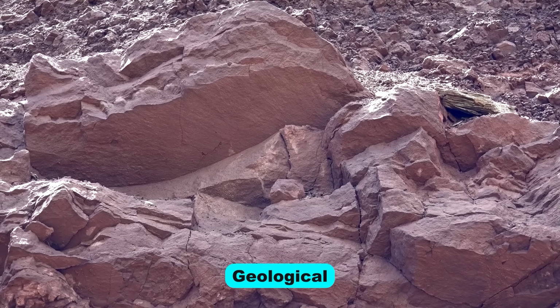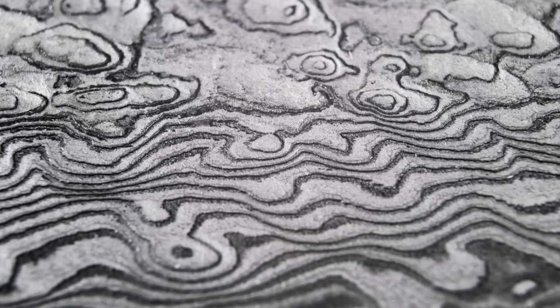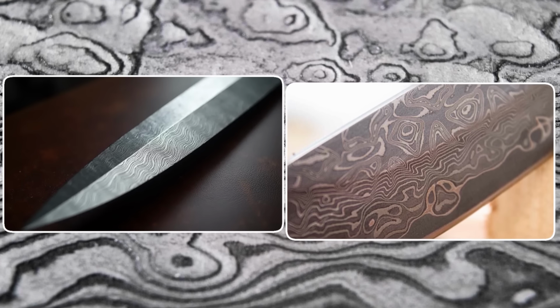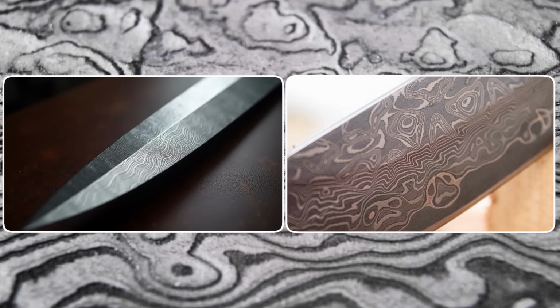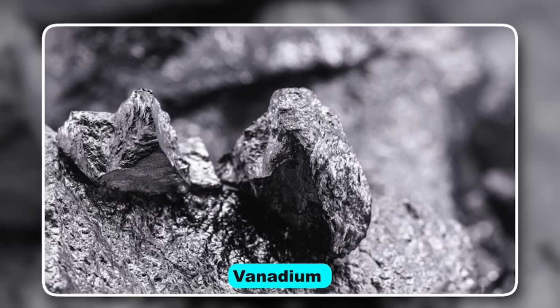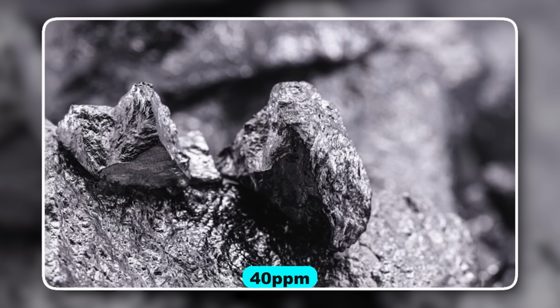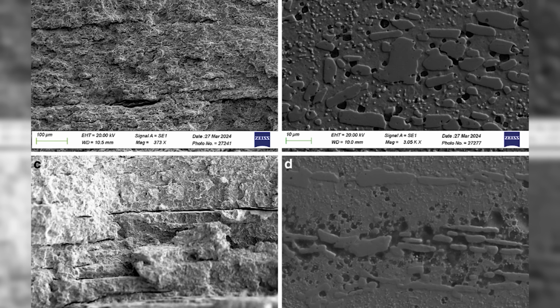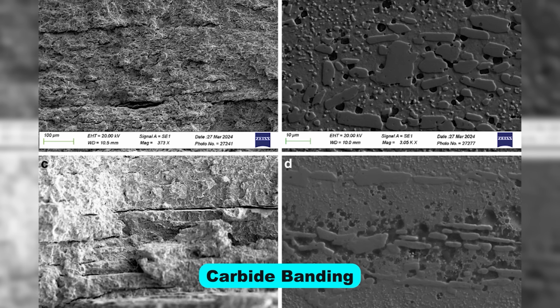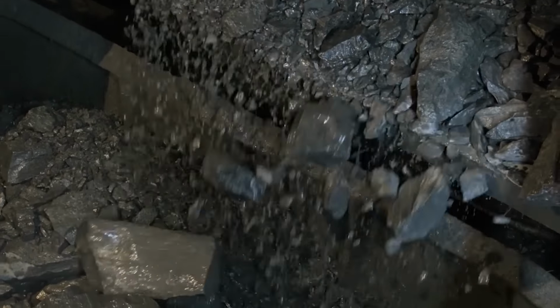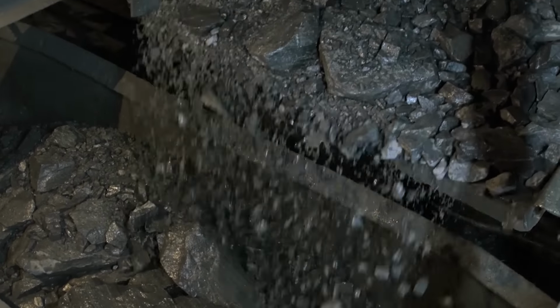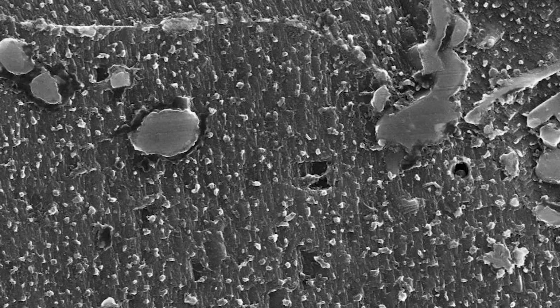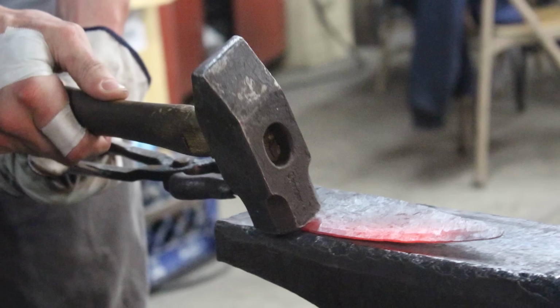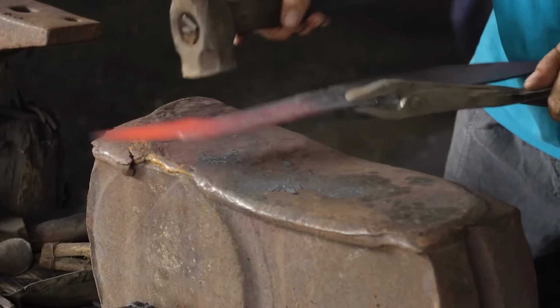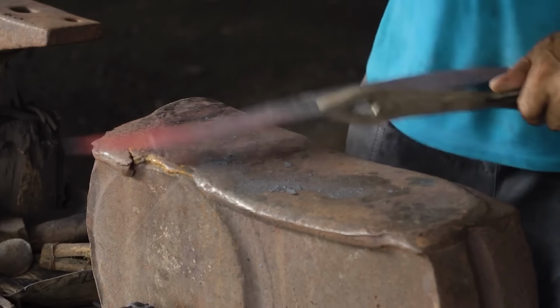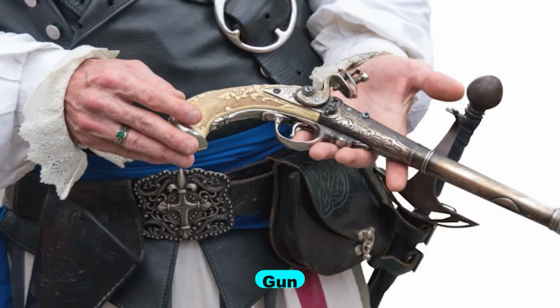The second force was geological. Verhoeven and Pendray's research demonstrated that the famous Damascus pattern depended on trace impurities in the original Indian ore, specifically vanadium at concentrations as low as 40 parts per million. Only certain deposits in certain regions produced steel that could develop the characteristic carbide banding, and when those specific deposits were mined out or became inaccessible through political disruption, the raw material for true Wootz disappeared along with them. Smiths may have continued making crucible steel, but the blades stopped showing the pattern, and without the pattern there was no Damascus steel. The third force was the gun.